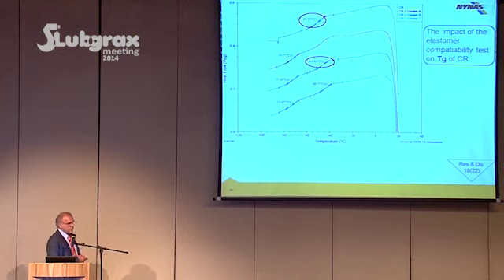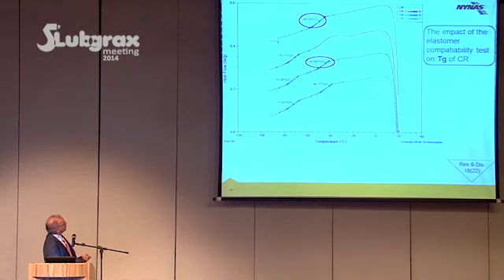So these are more graphs. What you see is the DSC on the rubber. We cool the product down, and what you measure here is the Tg, the glass transition temperature. What we see, for instance, is that these two products are okay. This is, in fact, group 1.